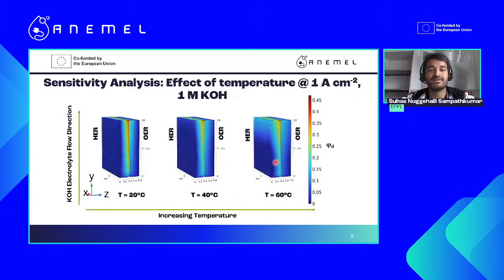So once we had a fairly good understanding of the simulation, we moved on to perform a sensitivity analysis by changing the state parameters. For instance, we changed the temperature from 20 to 60 degrees in 1 molar KOH at 1 ampere per centimeter square, and we could see that at higher temperatures you have better evacuation of the bubbles from the catalyst layer. The catalyst layer is close to the membrane, which is one of the reasons why we have enhanced performance, because the mass transfer kinetics are improved. And now we can visually see this.